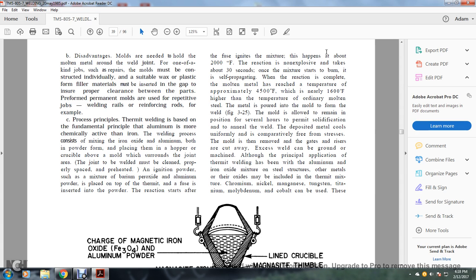The fuse ignites the mixture at about 2,000 degrees Fahrenheit. The non-explosive reaction takes about 30 seconds. Once the mixture starts to burn itself, propagating the reaction to completion, the molten metal reaches a temperature of approximately 4,500 degrees, which is nearly 1,600 degrees higher than the temperature of ordinary molten steel.